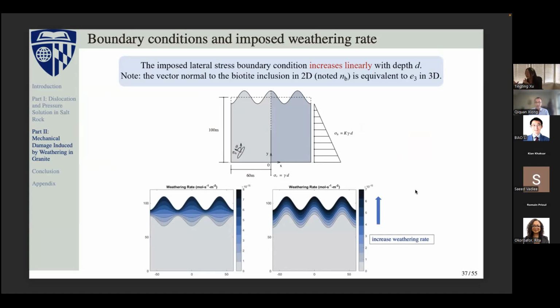You can see that for this field scale simulation, we have this kind of topography, a sinusoidal free surface, and we have the body force and the lateral earth pressure. And on the bottom figures, you can see that we have two different patterns of the applied weathering. What I want to emphasize is that for the boundary condition here, the stresses are constant, and the only driving force for the deformation is the weathering. So we apply two different types of weathering patterns, and more importantly, we have an increased weathering rate towards the free surface, which is understandable because the top surface has more contact with the environment, and we can imagine that the weathering rate there will be higher, and it goes lower and lower towards the bottom of this geometry.